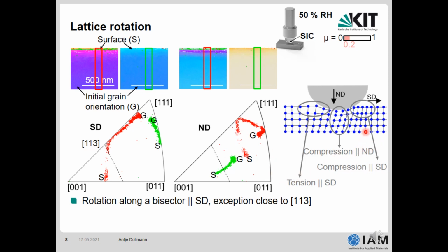I actually think that there is compression parallel to SD, then compression parallel to ND based on this normal load, and then here behind the sphere tension parallel to SD. And now we have a look at the inverse pole figures. We see here that the initial grain orientations are quite close to each other. So I actually think that SD was in this case not the important direction for the twin formation.